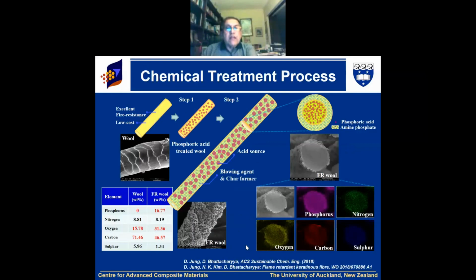So we noticed that we started with wool with phosphoric acid. If we look at this, I'm thankful to Daesung Jung because he understood chemistry much more than I did. So when we did with phosphoric acid and amine phosphate, we could actually penetrate, the phosphorus penetrated against the entire cross section. We were surprised ourselves. So when you do the analysis, carbon content and this has gone down, so we can do it improve that.